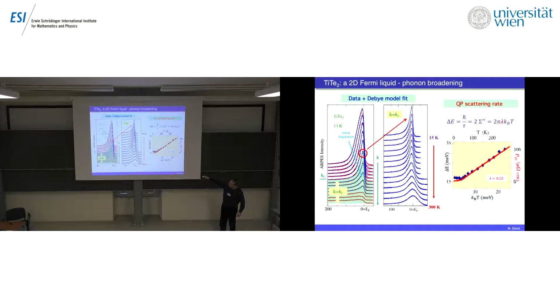Let's stick to the Fermi momentum, to this particular spectrum here, which is reproduced over here at 15 Kelvin, and then the same spectrum measured at a progressively larger temperature. And what you see is that there is a broadening, which comes from the fact that there are phonons that interact with the quasi-particle and contribute to the scattering rate. And in fact, one can plot the width of the quasi-particle peak as a function of temperature. It's the blue dots, and this goes very well actually with the resistivity, the electric resistivity of the same material. And this width is actually proportional to the scattering rate, or if you want, 2 times the imaginary part of the phonon self-energy.